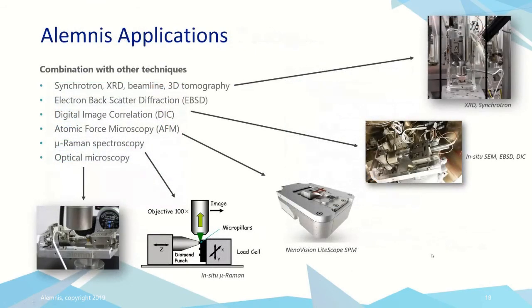The Alemnis system can also, apart from being combined with AFM here, we can also combine it with other techniques such as optical microscopy, micro-Raman. We often combine it with EBSD and also with digital image correlation, which allows us to get strain mapping of materials when we deform them. And we can also put it into a beamline or a synchrotron in order to do tomography experiments.